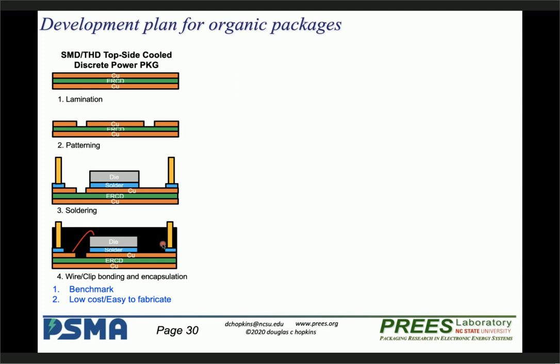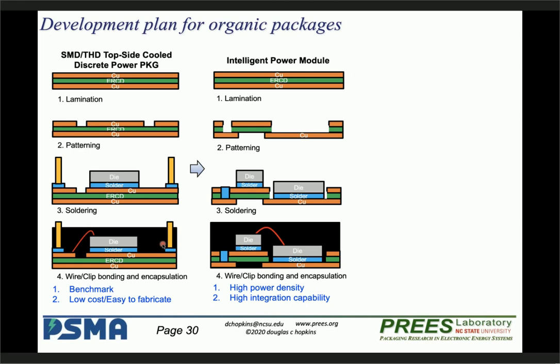Next, we focus on a patternable dielectric structure for integrating more devices in a single package, such as a gate driver or some passive devices. So you can see the second step. We not only do the patterning for the top conductor layer, the copper layer, but also the dielectric layer here, the green layer. Here's the structure we want to achieve: we can place the low power dissipation devices on the upper layer and the high power devices at the bottom layer.